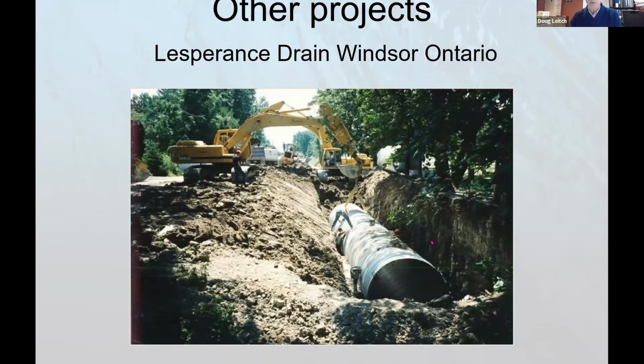Now, the spiral rib pipe wall is very, very thin, but in a situation with a concrete pipe, the walls may be as much as 18 inches wide, because they may be anywhere up to 8 inches in width on each side. So this was a very narrow place to fit in. So they're excellent pipes for where there's confined space and low cover.